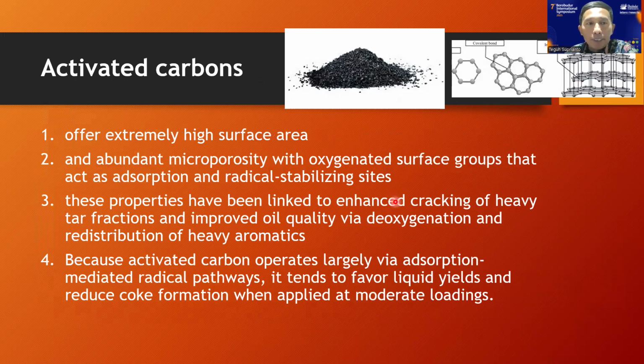These are the properties of the activated carbons. Activated carbon has special properties that support its activity as a catalyst. The first is that it offers an extremely high surface area. This is the most important property of activated carbon. The second is that they have abundant microporosity with oxygenated surface groups that act as adsorption and radical-stabilizing sites.